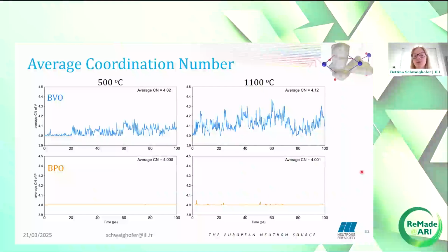As a first sanity check, we looked at the average coordination number during the simulations. Since the main difference between the materials is that vanadium readily supports variable coordination environments, whereas phosphorus doesn't, we expected the coordination number in BVO for the vanadium atoms to change significantly. This is the case, as you can see, both at 500 and 1100 degrees Celsius, where for BPO the average coordination number of the phosphorus atom stays close to 4 during the whole simulation, whereas for BVO it reaches an average of 4.12, which means that 2 out of 16 vanadium atoms in the structure are on average 5 coordinate.